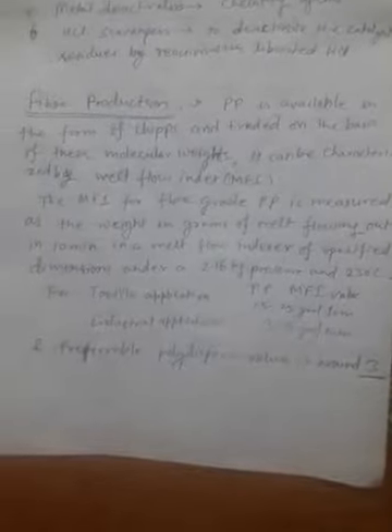The melt flow index for fiber grade PP is measured as the weight in grams of the melt flowing out in 10 minutes in a melt flow indexer of specified dimensions under a 2.16 kilogram load at 230 degrees centigrade. Through a melt flow indexer one can check the MFI value. For textile application, textile grade polypropylene polymer, the MFI value is 15 to 25 gram per 10 minutes, while for the industrial application polymer grade it is 3 to 5 grams flowing through that specified dimension tube in 10 minutes.